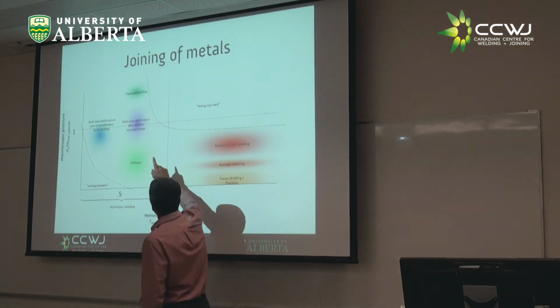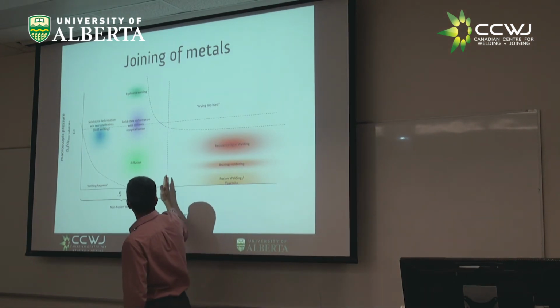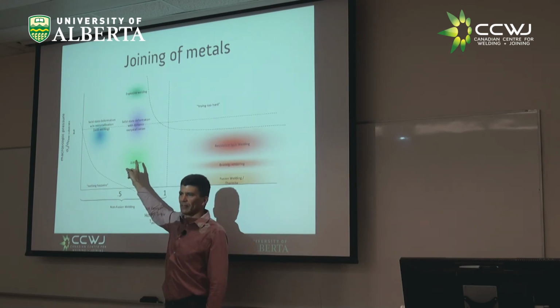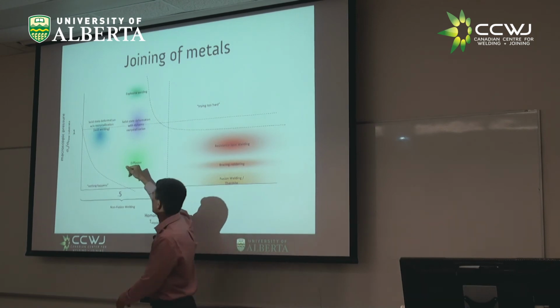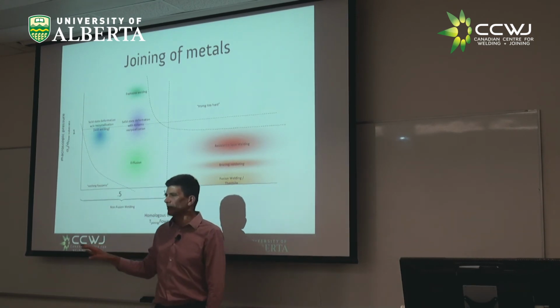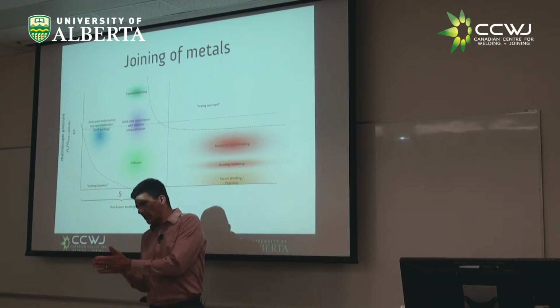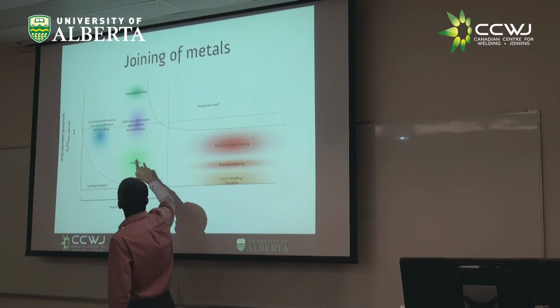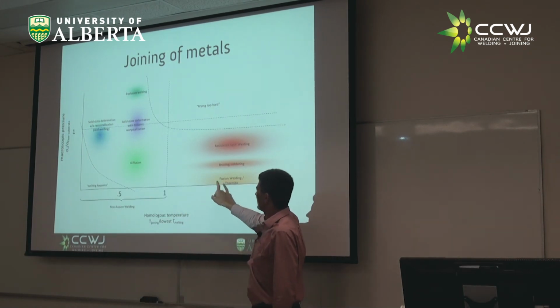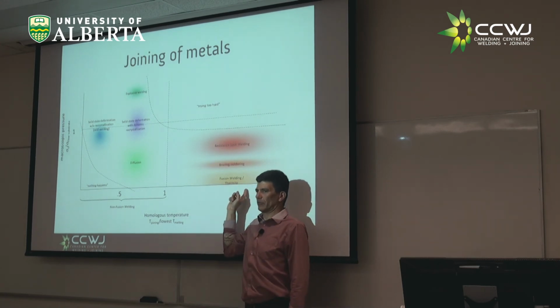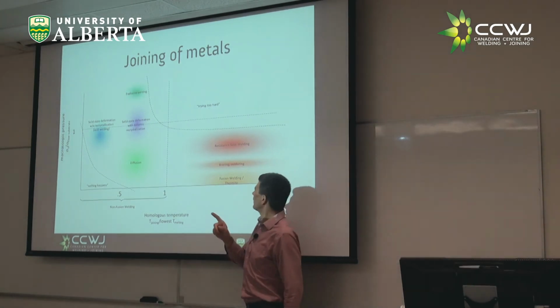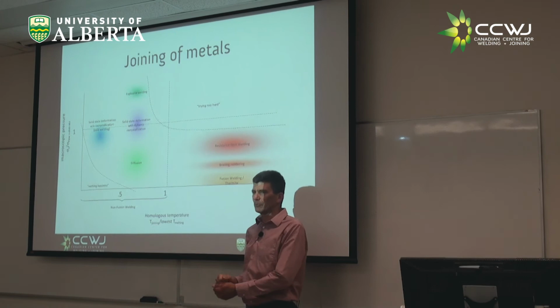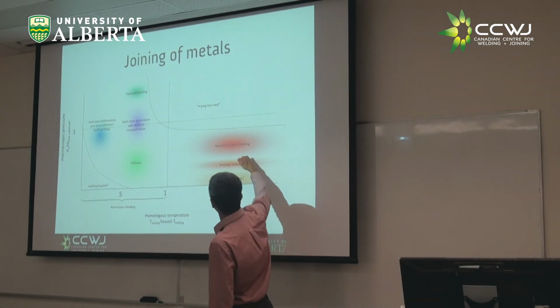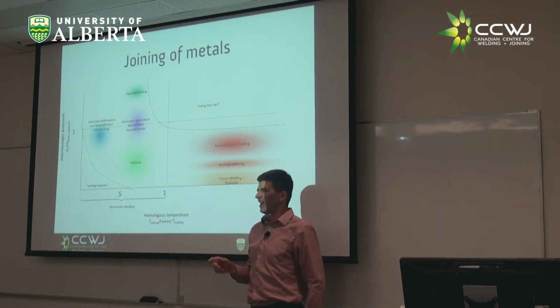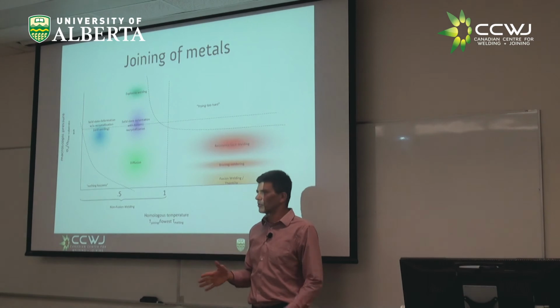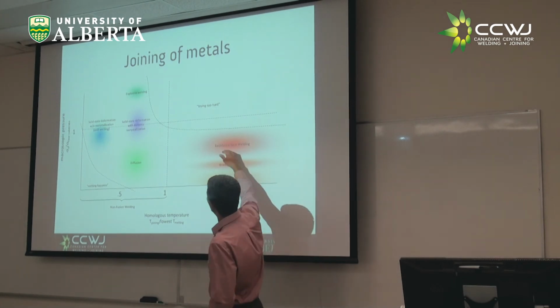So let's think. Diffusion, that means we have a low homologous temperature. Nothing is melting. Remember? Nothing is melting in diffusion. Nothing should be melting. And the pressure should not be too high either, right? The pressure is not too low either, because we want to have at the beginning a good contact. I put diffusion here. Let's talk about fusion welding. Has to be more than 1 here, because something has to be liquid. But no pressure, right? Unless it's resistance spot welding. Because if I do that, I'm going to squeeze out all the molten metal. Brazing and soldering. I do have something liquid, right? I have my braze and my solder. But you need a little bit of pressure just to keep the parts together as the process is happening.